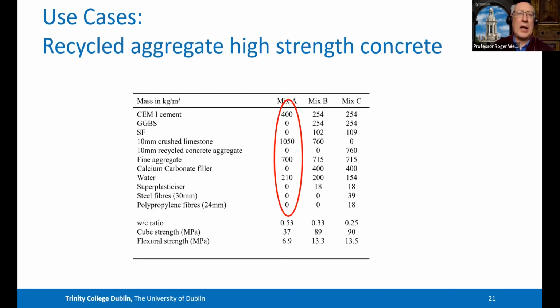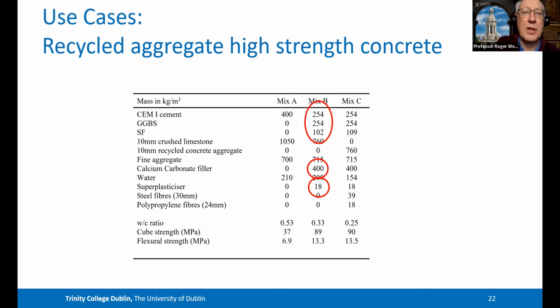So let me give you an idea as to how we can develop recycled concrete, because there are these myths about it can't really be used in terms of maintaining strength. So here's the typical mix quantities that we saw before. And nothing unusual about that. But when we go to replace the cementitious materials, and here you can see there is a higher quantity of cement there in order to achieve high strength. So we're getting about 90 megapascals. So this is high strength concrete using